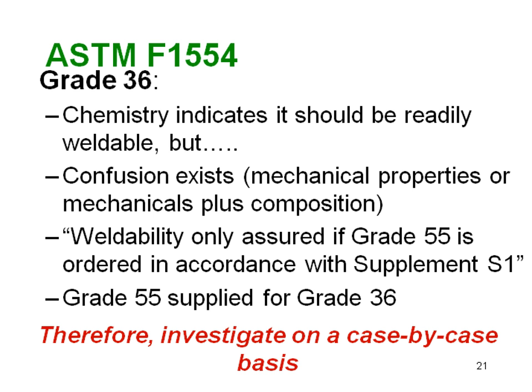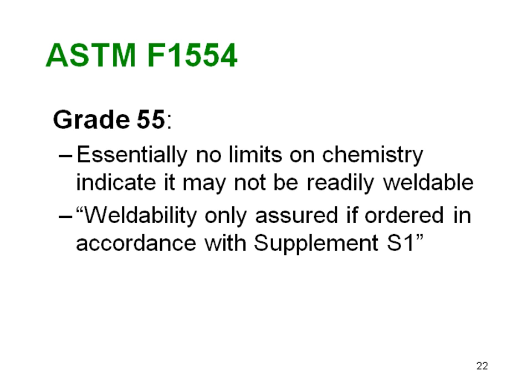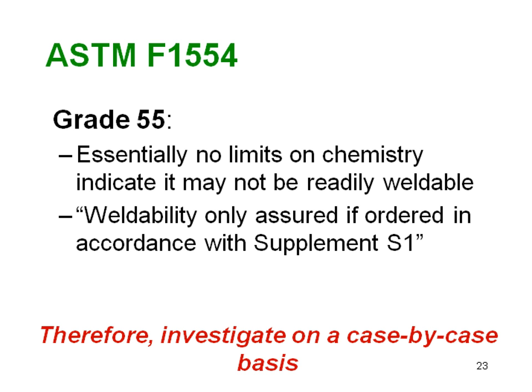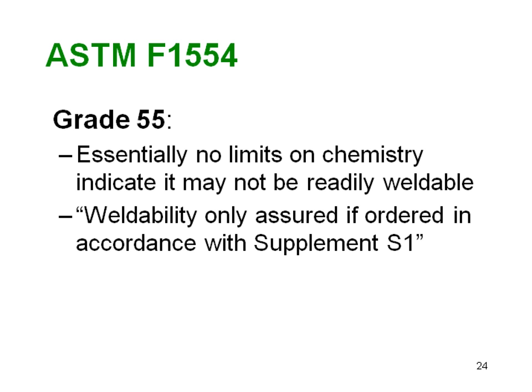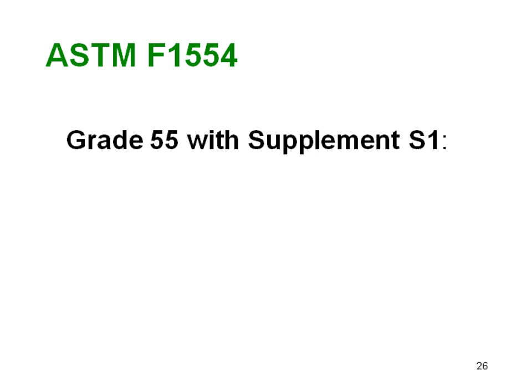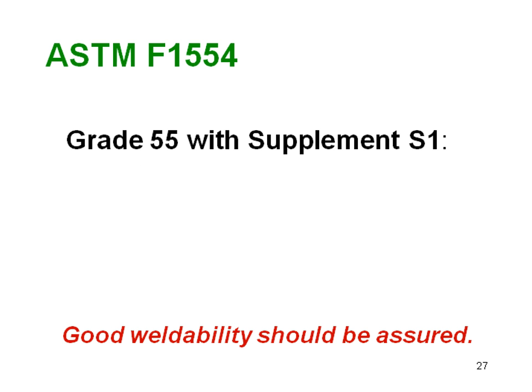Now, when we go to grade 36, we're essentially in the same boat as when we go to grade 55, because we might have that substitution. We have no limits on chemistry. We have this note that says it's not assured to be weldable when we order it other than with supplement S1. I come to the conclusion that, once again, investigation on a case-by-case basis is required. Now, grade 55 that's ordered in accordance to supplement S1, well, there I should have pretty good confidence that my weldability is going to be fine.